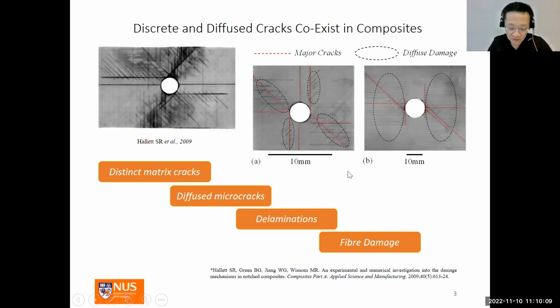If you read the early literature, let's say in the 1980s, on notched composites, you will come across criteria such as a point stress or average stress criteria, which are essentially empirical criteria, not really based on much physics. Therefore, for every change in laminate stacking sequence, or let's say an OHT specimen, you will then have to vary the critical stress and so-called characteristic length. So for thousands upon thousands of specimens, you may have very different criteria. So clearly, this is not a satisfactory situation. Fortunately, our understanding and modeling of progressive damage has improved considerably since then. Our models have also evolved in sophistication, as we shall see.